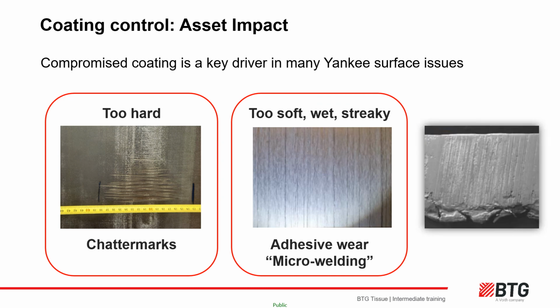The final picture is actually one of a steel blade in contact with the dryer when coating has been washed away. The bits hanging at the bottom are actually part of the Yankee cylinder surface being transferred to the blade by adhesive wear or micro welding.